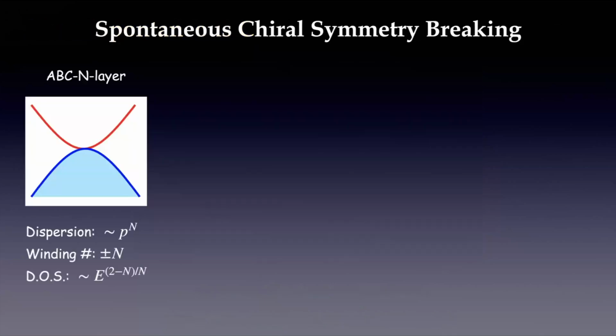Okay, so it turns out, if you calculate the density of states, it will be 0 at the Dirac point in single layer graphene, is a constant in bilayer graphene, and becomes divergent for n bigger than 2 systems. Okay, so if I translate that into theory language, if we do a perturbative RG calculation using constant interaction, that will say in the n equal to 2 bilayer system, the interaction is going to be marginally relevant. Okay, so it's really strong. And in n bigger than 2 systems, the interaction is already relevant at tree level.